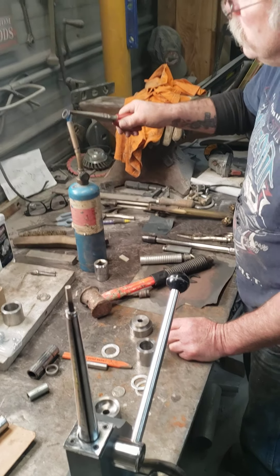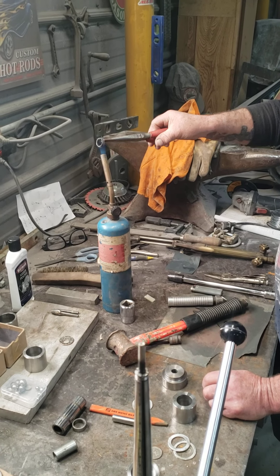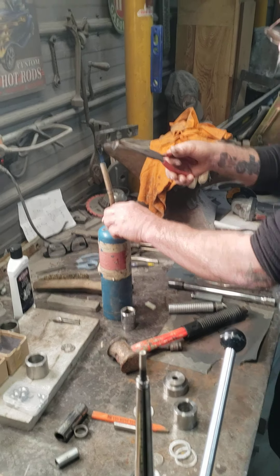Using a silver quarter, or just a regular quarter? It's just a regular 1984. I'm surprised you didn't try silver. Nickel copper — this actually works better than silver. Silver cracks and it's harder to use. You have to heat it up? Yeah, just like this. You've got to anneal it also. That hardens it? No, that softens it. When you put it in water, it softens it? Yeah, this is annealing it.